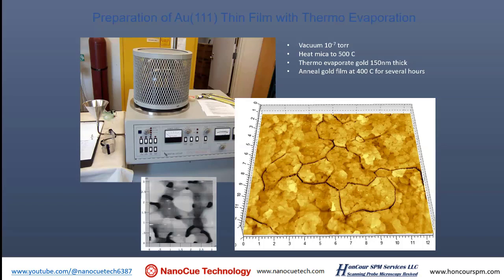However, a lot of the time your gold surface is not very flat, because your temperature annealing is not right, or something's not right. As a matter of fact, when I started my career with self-assembled monolayer research as a graduate student, I had a lot of samples that looked like the one on the left corner, with a lot of smaller grains. There's no flat surface. That makes it very difficult for you to find atomic steps, zoom in, and do AFM and STM on it.